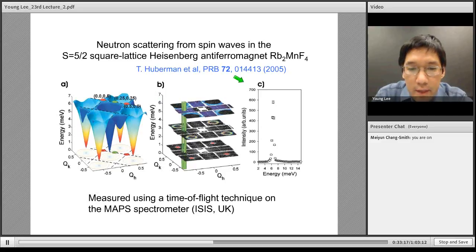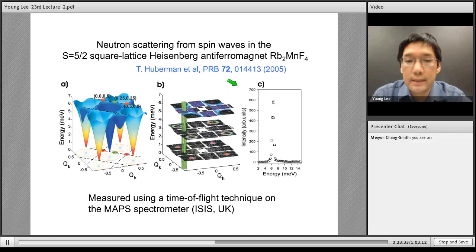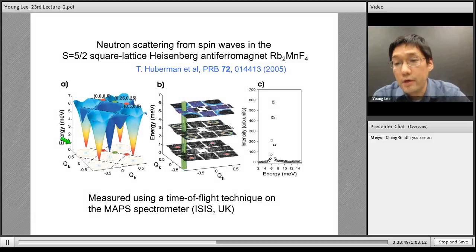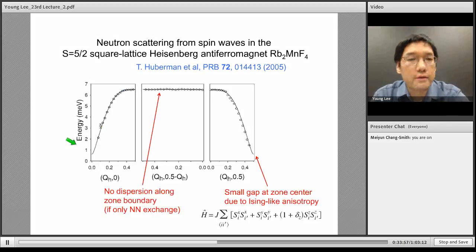This final panel here, I believe, was taken along this green line in the middle panel, and you can see that when you cut through one of these cones of scattering, you get a very sharp peak. Again, these spin waves should be delta function sharp, just convolved with your instrumental resolution to give you the width. I think it's very clear that you can see in their data something that looks like a very linear dispersion from the zone centers, which is different than the ferromagnetic case, but this is what we expect for the Heisenberg antiferromagnet.